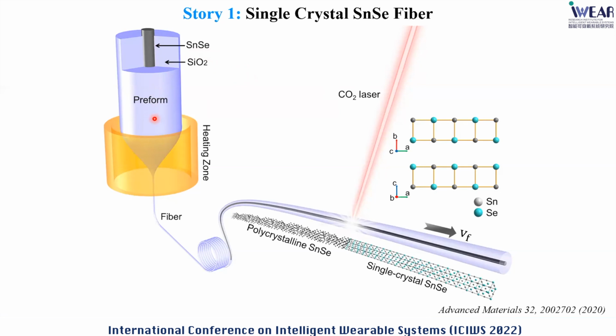After the thermal drawing, because of the cooling effect from the surroundings, we end up with a semiconductor core with a glass cladding. But if we look at the crystal structure of this semiconductor core, it is polycrystalline. This is simply because when we cool it down, there is a temperature gradient from the surface to the core, so we cannot have a fixed crystal orientation. And if we cannot get a single crystal, the device performance will be compromised.